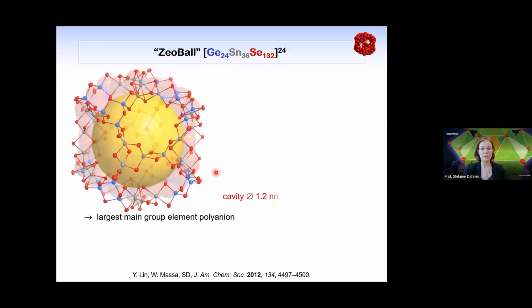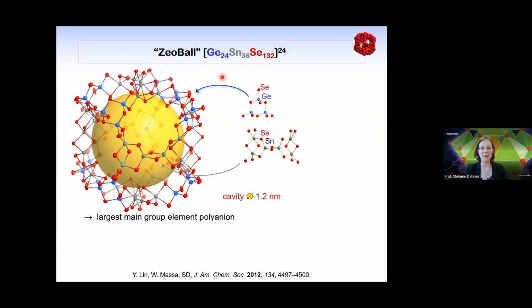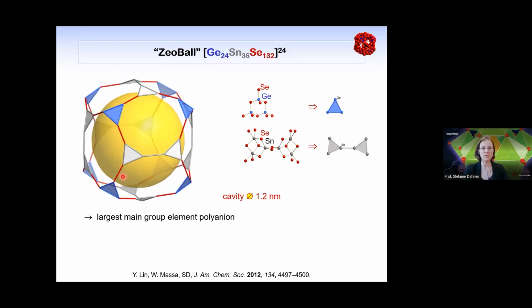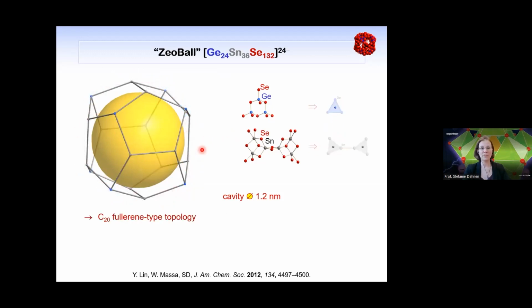Let's get back to this crystal structure and just have a look at the initial anion. This is a very huge anion made up of 192 atoms. It's actually the largest main group element polyanion that has been reported, and it has a cavity inside about 1 nanometer in diameter. To explain the structure a little bit more in detail, here are the structural units that make up this cluster. It's a tin selenium-based and a germanium selenium-based structural unit. To simplify these two structural building units, I just draw the group 14 elements now, which gives you this view. And if we just place a center of gravity here, then you will end up with a very simple topology.